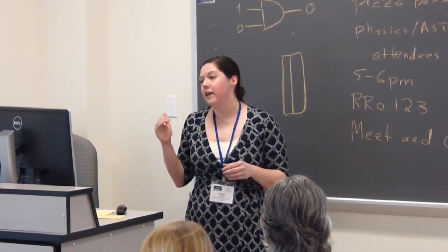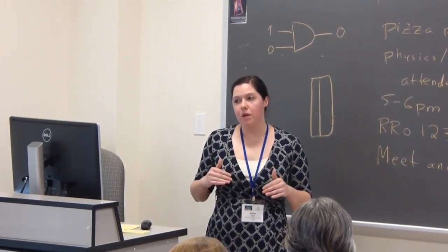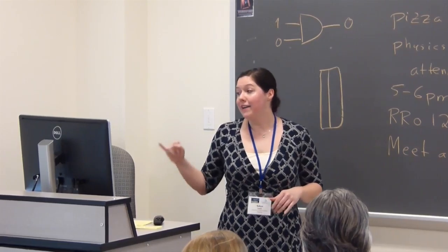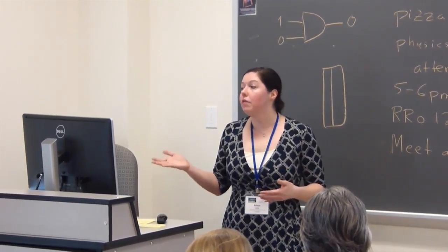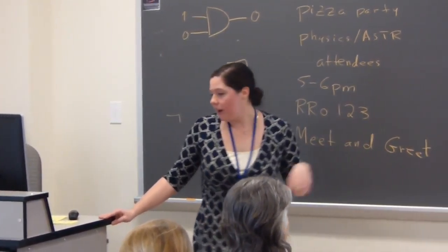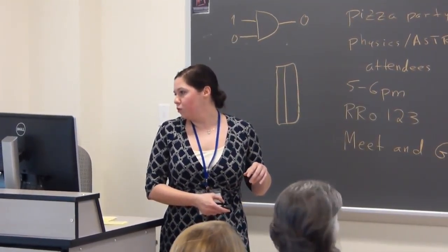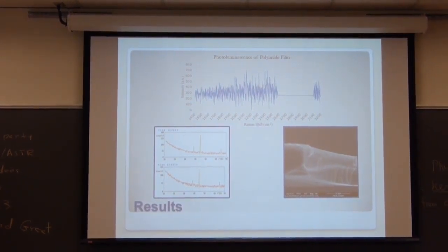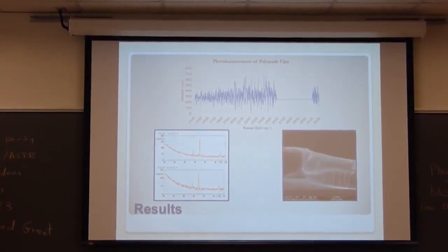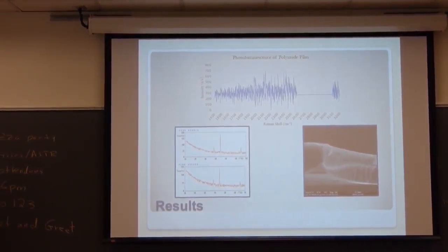And that's really going to be the big one. Also, one of the things is that in Raman spectroscopy, you want to be able to subtract the effect of your substrate from the material that you're looking for. And this is essentially broad data. I mean, it's put into a very nice presentation. But, we're not seeing any of the noise that we saw in this top one. And this was just polyimide. My hope is it's because we turned the polyimide into graphene. And so, that is what we're seeing. But, that's another factor that we're going to have to look at and see whether this actually was a positive result.